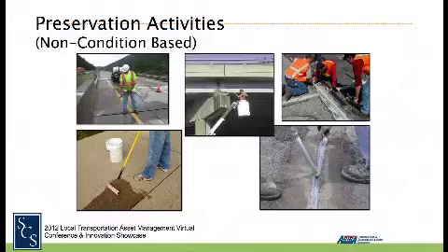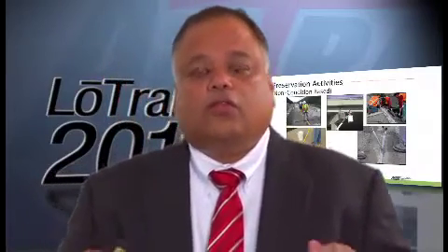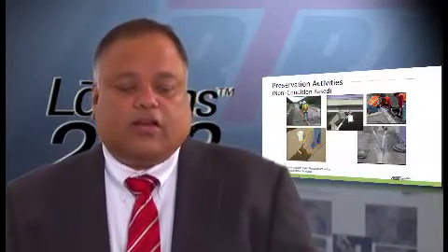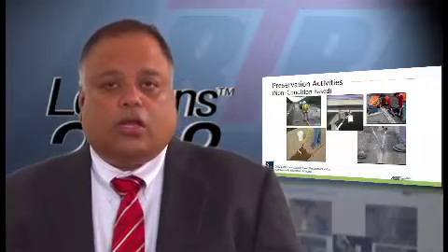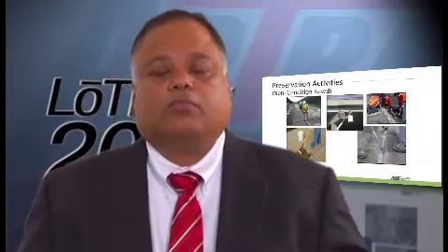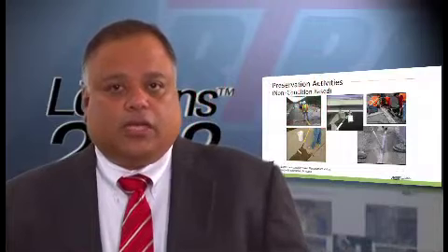Or if you have a deck and it's leaking, you want to fix that so that you don't allow the salt to go in and corrode whatever is underneath your deck. And if you have a new deck, instead of just exposing it directly to de-icing salt, you seal the surface, which then allows you to slow down the salt from going into your concrete and start corroding the deck. So there are several things that you can do that are not condition-based, but are preventive activities that actually increase the time to deterioration, the first problems that you get to see.